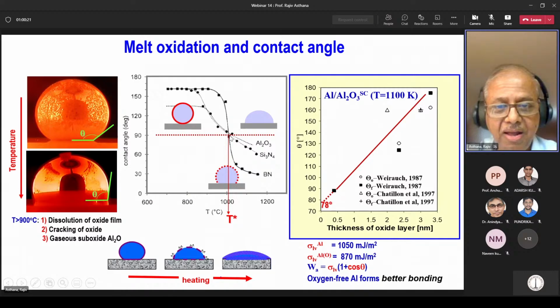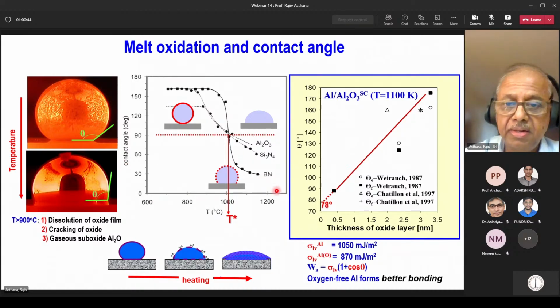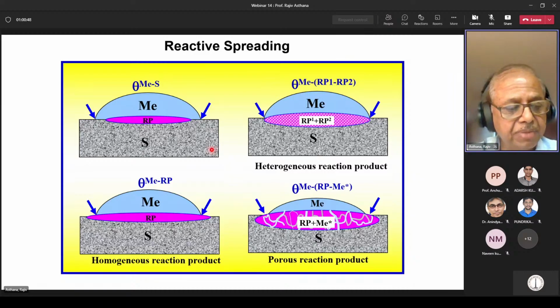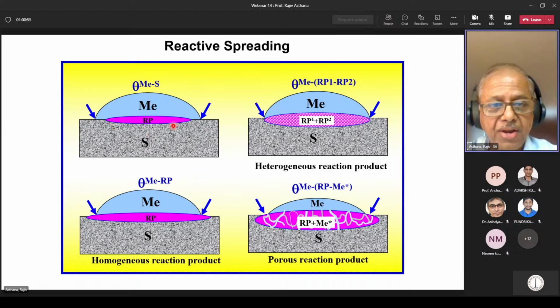What that means is that up until this temperature, oxide skin on the liquid droplet interferes with the spreading process. Above about 1000 degrees Celsius, you can see that the contact angle on each substrate is different. And that is what we expect also. So in the system that we study, there could be reactions taking place between the liquid and the substrate. So the reaction layer could grow at a rate slower than the spreading of the droplet. When that happens in a system, the liquid is contacting the original virgin substrate, not the modified surface.